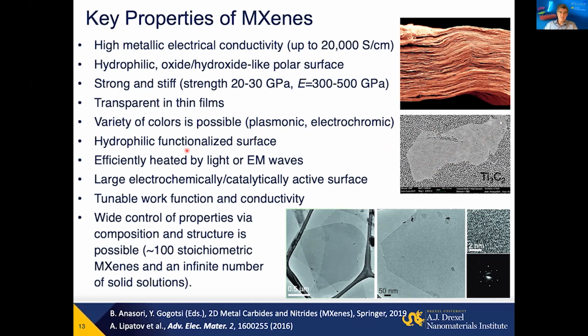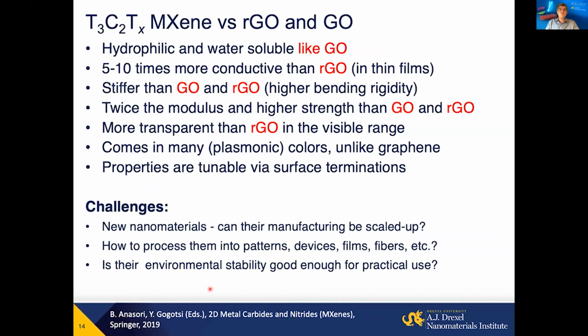They have a hydrophilic functionalized surface and also efficiently absorb electromagnetic waves. But what is important, we have again more than 100 stoichiometric MXenes predicted, more than 30 already reported, and a virtually infinite number of solid solutions, so we can control and tune those properties here.